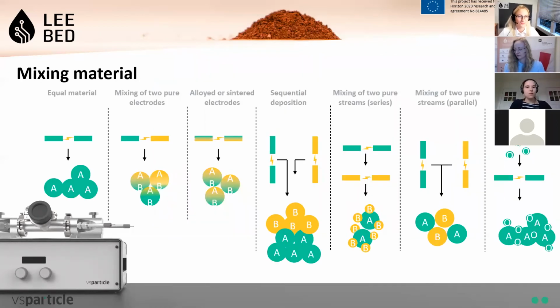The generation unit offers several methods to mix material. If you use two electrodes of the same material, let's say A, you of course get nanoparticles of material A. If you use two different electrodes, you can make a composite with a fixed ratio. If you really want to control the ratio, then you can use alloyed or sintered electrodes to get to the desired ratio of material A and B. But you can also use two generators in parallel to mix the materials then in the gas stream with a ratio that you can determine via the input parameters.